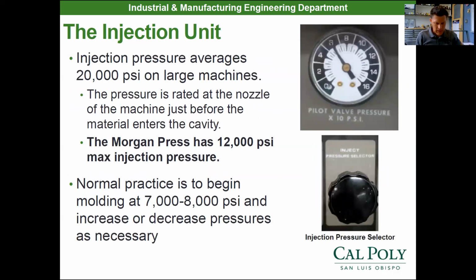Now, once the mold's together and clamped and the nozzle's up to it, you have to set the injection pressure on the machine. Injection pressure is really rated off of how viscous your material is and how big of a cavity you have to fill. Do I have to fill a large cavity? Do I have to fill a really thin cavity? Do I have a lot of passageways that might need a little bit higher temperature and higher pressure in order to fill them? It really just depends. Our press has 12,000 PSI max injection pressure, and to be honest with you, we're running 6,000 PSI.